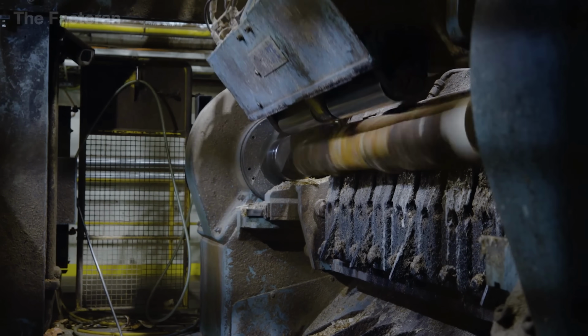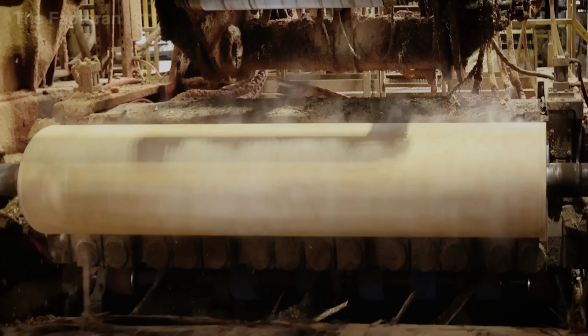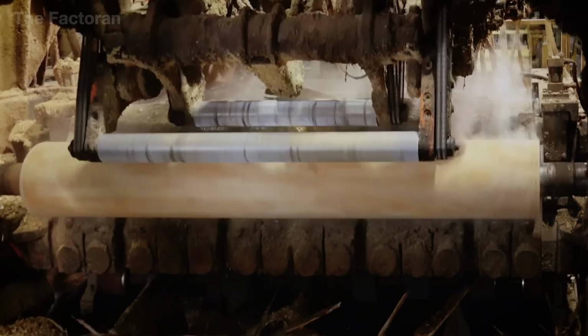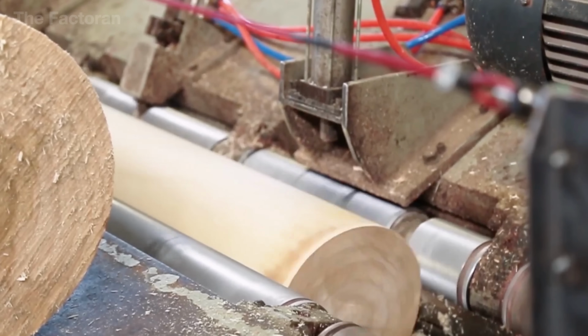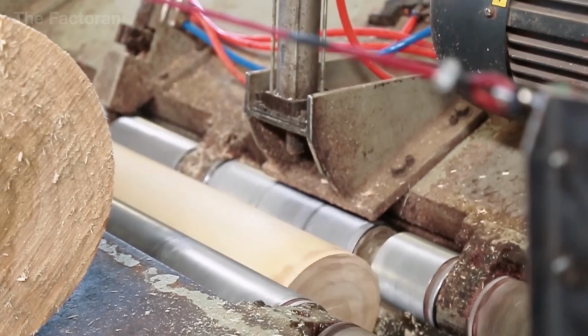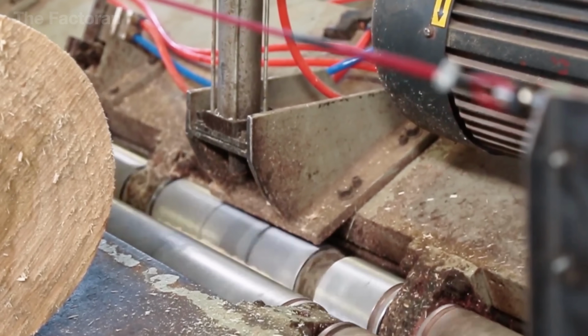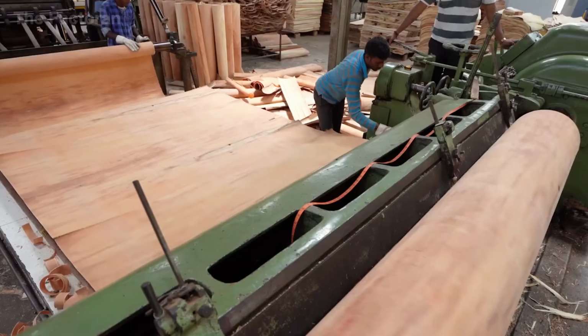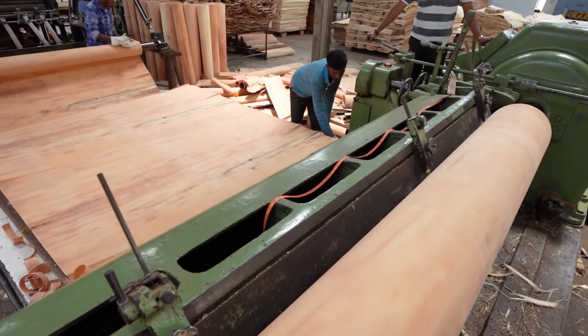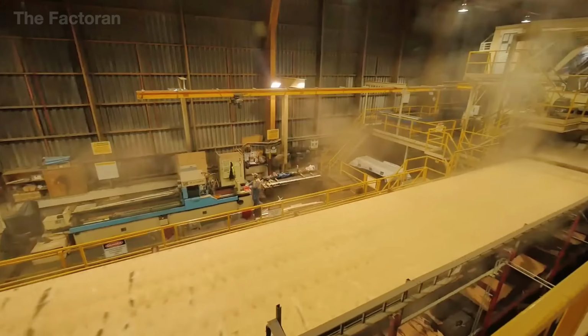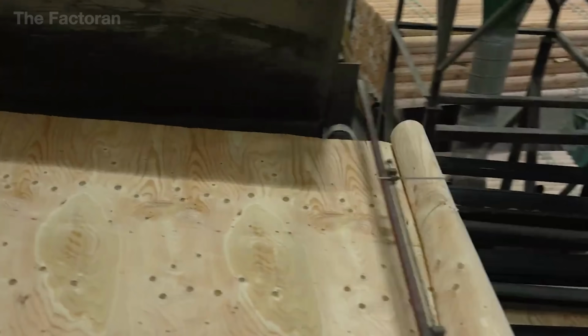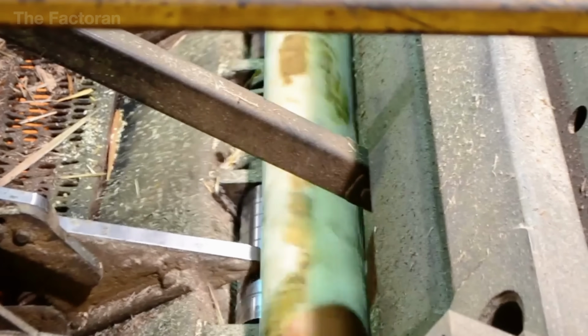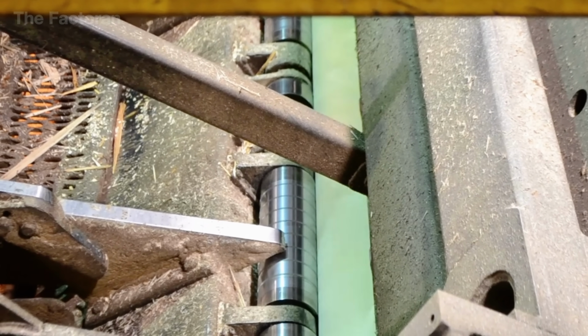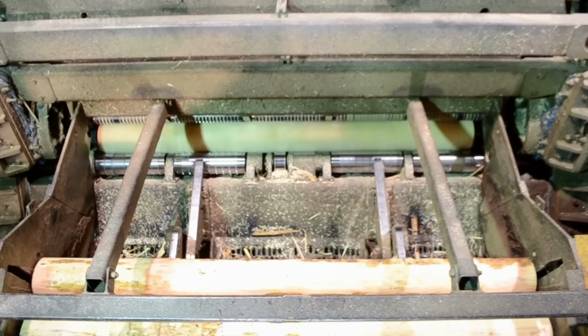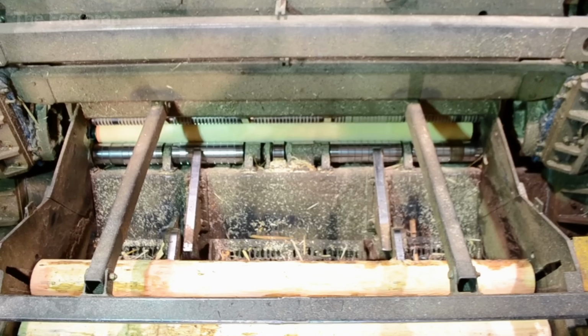A steel knife more than 3 meters long, sharpened at an angle of about 20 to 23 degrees, presses firmly against the surface. Opposite it, the nose bar applies steady pressure, compressing the fibers and preventing cracks during peeling. With each revolution, a thin veneer layer, only 1 to 3 millimeters thick, is sliced away, unrolling in a continuous wooden ribbon. Veneer thickness is precisely determined by the micro-adjusted distance between knife and spindle, combined with rotation speed. A deviation as small as 0.1 millimeter can render an entire sheet unusable.